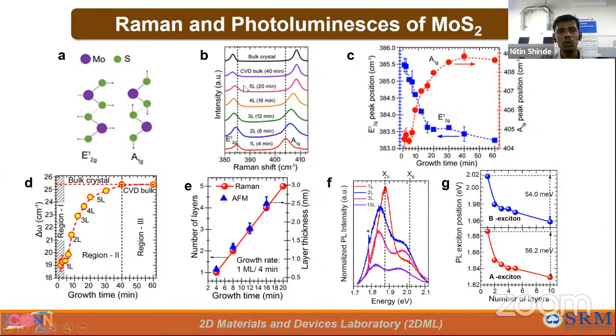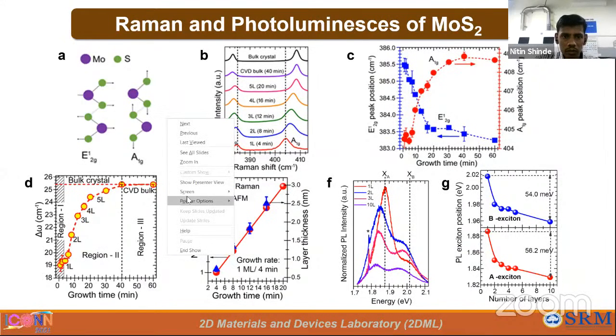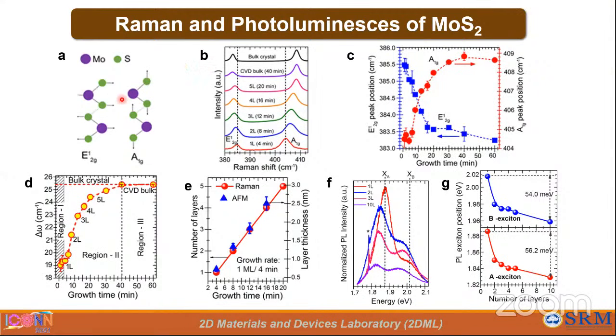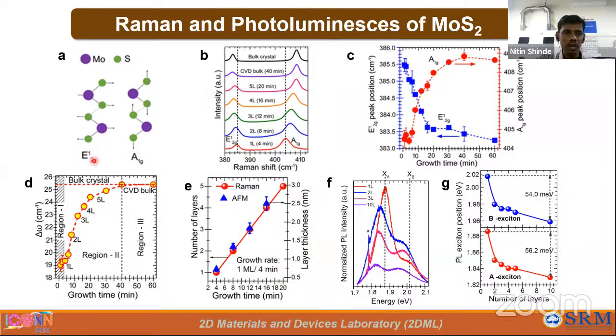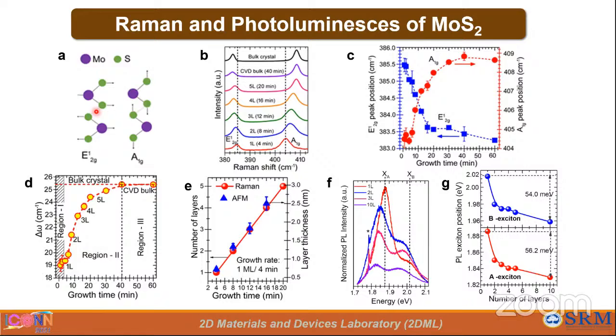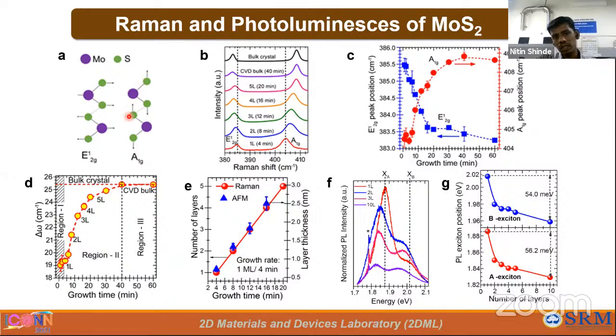Raman is a very good technique to analyze 2D materials. We are taking advantage of Raman spectroscopy to identify the number of layers of MoS2 in the deposited sample. In Raman of MoS2 there are 2 active modes, E2G1 and A1G. E2G is the in-plane vibration of molybdenum and sulfur atoms, and A1G is the out-of-plane vibration of sulfur atoms. We deposited different samples by only changing the growth time from 1 minute to 60 minutes.